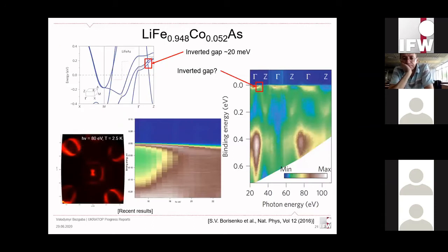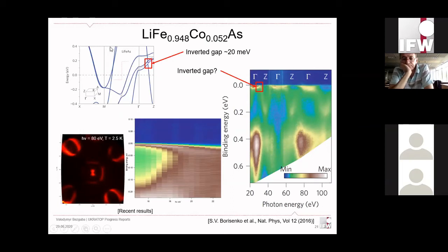In our scenario, there are very well known calculations from Sergei Borisenko's group from the paper in Nature Physics 2016. Here, the size of the band inverted gap is around 20 meV, and we have also, from the past, a very nice kz map, mapped from 20 to 100 eV, very detailed. And here, unfortunately, it's not possible to see the inverted gap at this side of the Brillouin zone. So we got interested, maybe we can see it if we go lower in the energy, to map it from 20 eV and below, as low as possible.